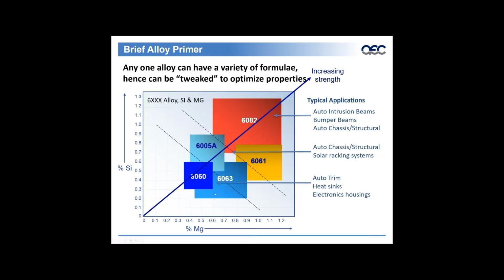Now this alloy, 6060, and we see some overlap with a 6005A and a 6063, tend to be alloys that can be quenched with the utilization of air only. The result of that is tighter tolerances, less twist, and less bow, which result in better downstream assembly, welding, and fabrication.